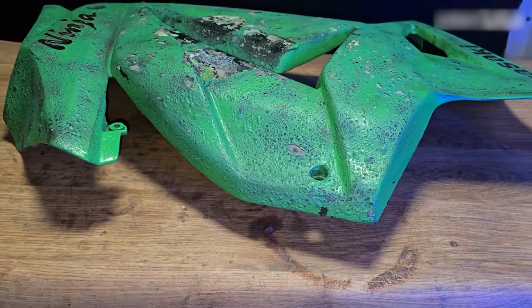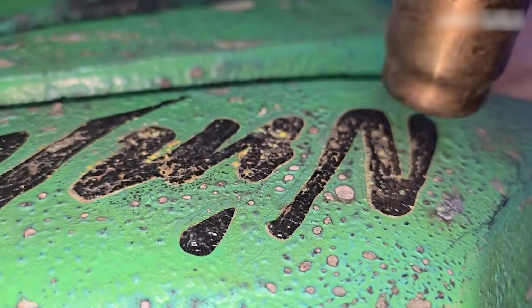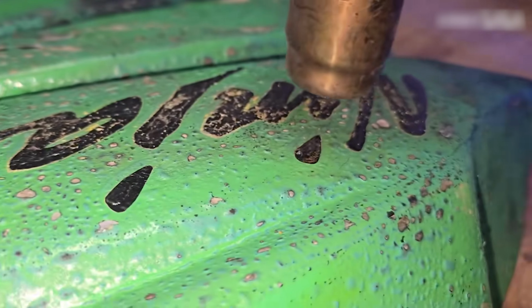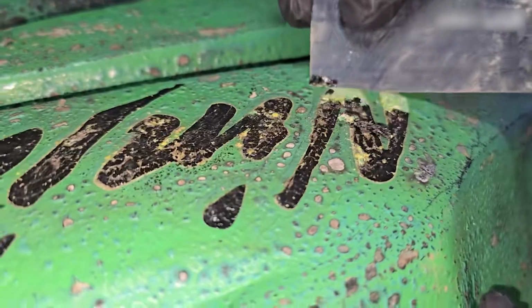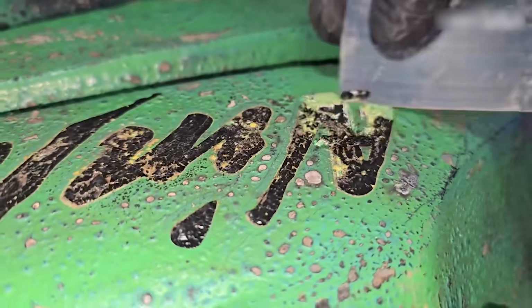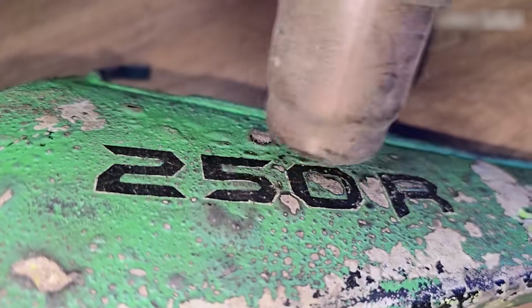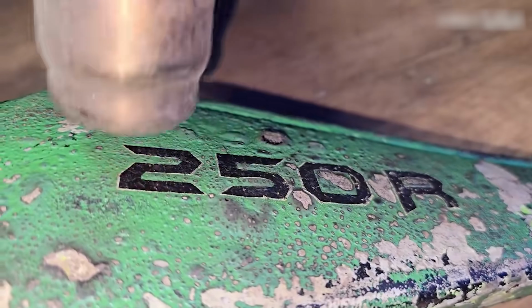These fairings are ABS, acrylonitrile butadiene styrene. 3 decades of UV exposure triggers photodegradation, breaking down the polymer chains until the plastic can no longer flex without fracturing. Removing this compromised layer requires the care of surgery when cracked and the original mold is lost.